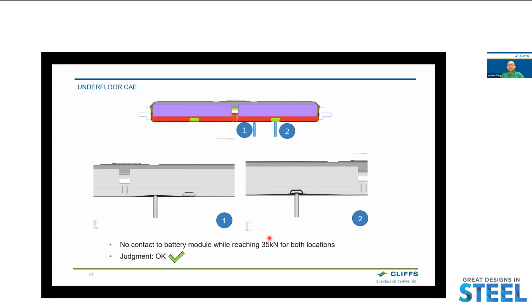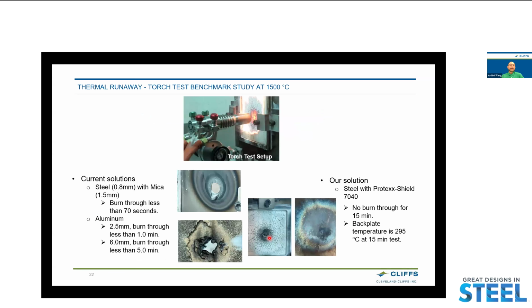So for the thermal runaway test, our partner at Tenneco have conducted a series of component level tests. On the top shows the setup for the torch test. Our solution of using the steel with Tenneco's Protex 7040 and 7045 provide excellent thermal runaway protection. No burn through in 15 minutes.